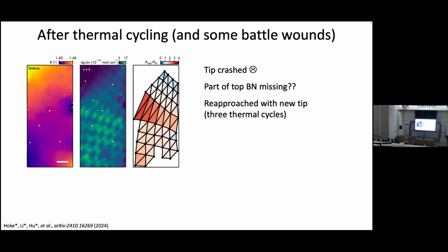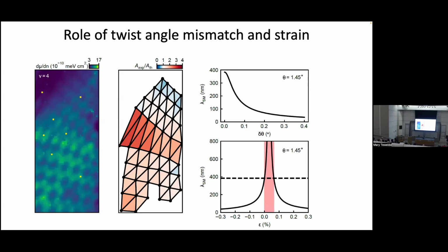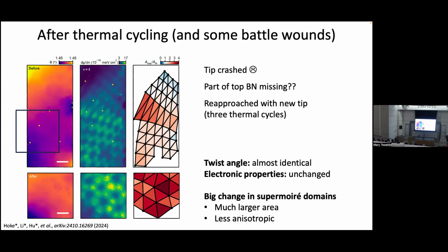I'll point out, again, it's only select values, a small subset of the possible strain values, which will give you this enhancement. So I think fundamentally what's happening here is that energetics is helping us. That is, there is a certain preferred stacking, and there's a competition effectively in terms of how big you want these domains to be. It's a typical stat-mech problem. There's some costs associated with these linear boundaries.